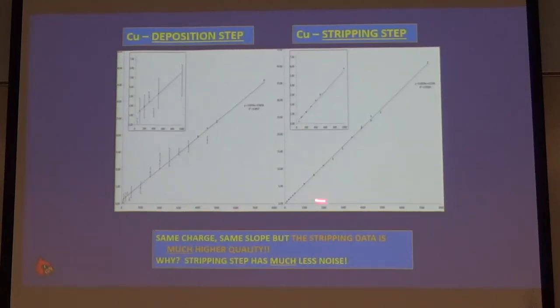But this is much higher quality data for the stripping step. You see the uncertainties in the charges we're measuring for the deposition. Well, why is that? Well, the deposition takes a minute, and during most of that minute, the signal is very, very small. So that's low quality data most of the time. The signal to noise ratio is poor for this stuff. But here, we're only integrating for less than a second, and so there's much less noise being built into the signal.